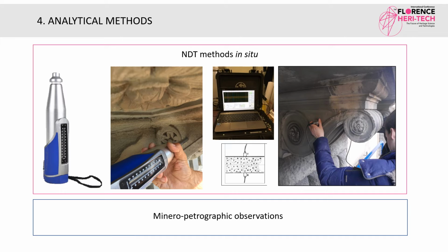From the rebound value R, it is possible to obtain the evaluation of the surface hardness of the material. Ultrasonic test makes it possible to detect cracks and other discontinuities, clarifying the level of damage. The ultrasonic velocity values Vp are related to the mechanical properties of the stone, such as elasticity, density, and porosity. The measurements were performed in direct transmission mode.